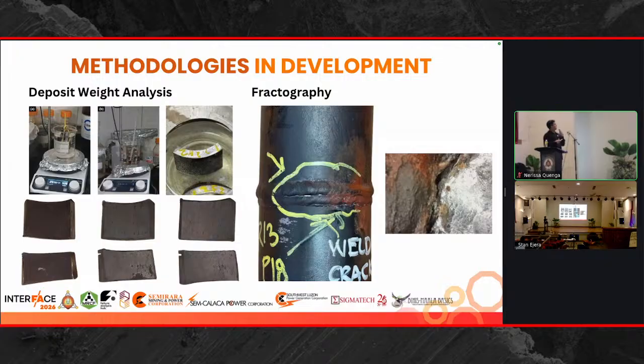So we use chemical reagents to strip off the deposit scales, and we calculate the loss of mass recorded from its initial condition to the immersed condition, so that we can quantify if the part needs cleaning or not. And deposits in boiler tubes can cause inconsistencies and deviations in heat transfer within the tube walls, which may cause localized heating and eventual failure. So this is a really important testing for boiler tube applications.